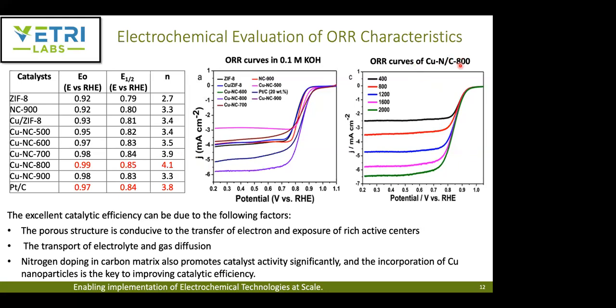And this is to just show how the ORR curves at different RPM vary for this best functioning catalyst, CuNC 800. As you can see, this is mass transfer limited, so that's why you see this steady state plateau. But with respect to rotation rate, you will have more oxygen getting to your electrode. So you should have an increase in the current density, and they could confirm that by changing the rotation rate, the current density indeed increases.